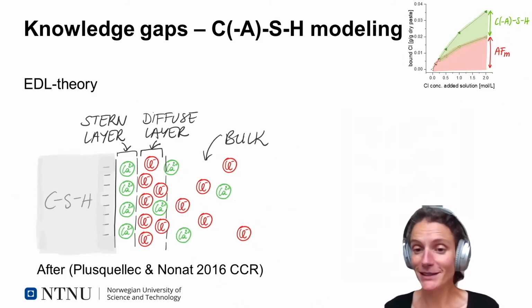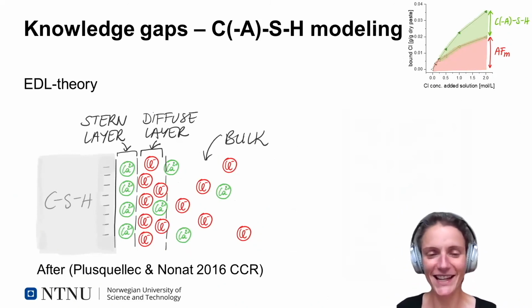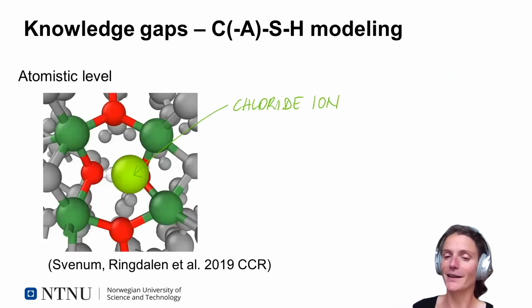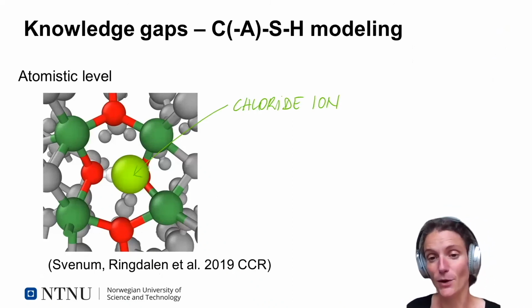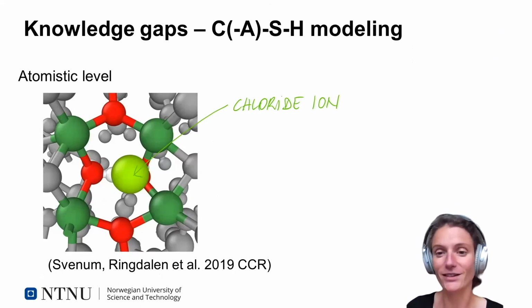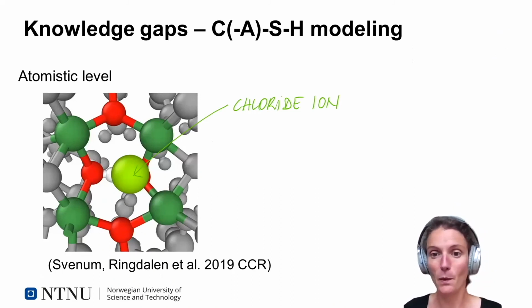And then we come to the black box, CSH or C-S-H. In literature, the interaction between CSH and chlorides is often described using the EDL theory, which I described earlier when I wanted to explain the cation effect. So recent advances in modeling of CSH on an atomistic level are showing very high potential to start to know more about how the chloride actually interacts with the CSH. What are the forces working on the chloride? Would it at all? How does it contribute potentially to diffusion?